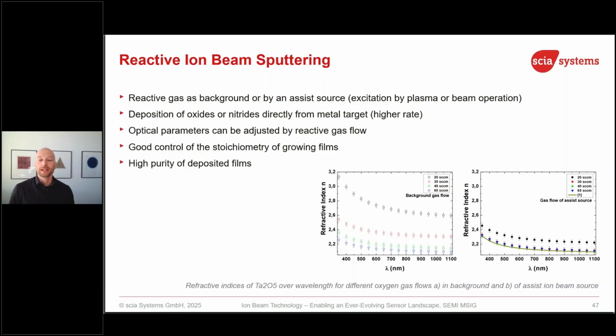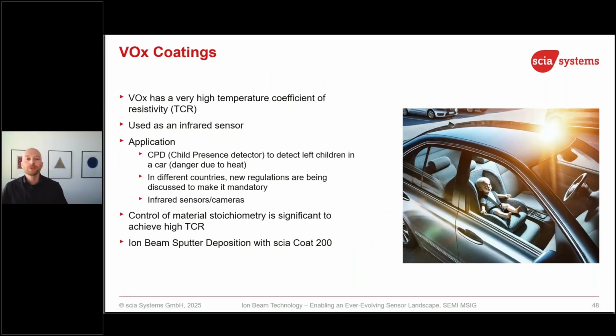So we just have a metal target. In that case, we have some measurement data for tantalum pentoxide. And depending on the oxygen flow, what is shown here, we can tune the refractive index of our layer. Means it's going from fully oxidic to more like a metal mode. And this could be used in order to make vanadium oxide coatings, which are used as an infrared sensor.